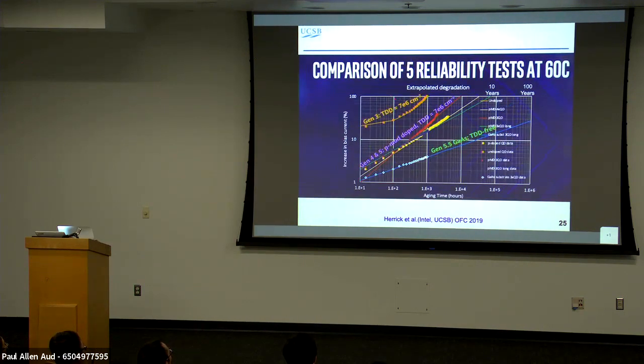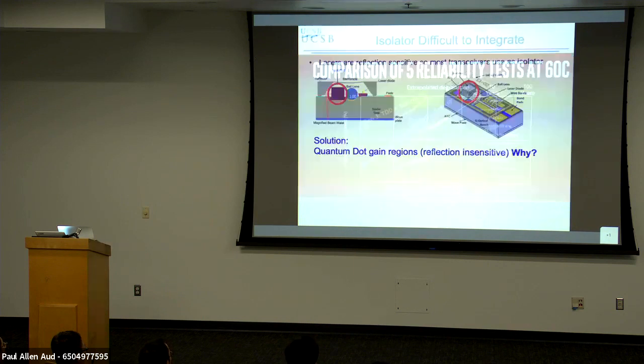And here's the answer. So that previous 7×10 to the 6th that was out to here at room temperature now dies in a few thousand hours. But as you do other things, we're calling Gen 4, Gen 5, they're all p-doped devices. They're on the order of 2 orders of magnitude better lifetime. And so this is kind of where we stand today, around 10-year lifetime in devices at high temperatures. So it's not good enough yet, but it's getting closer. Our quantum dot lasers on gallium arsenide have much better lifetimes. And again, there's no dislocations. So we're still dislocation limited in terms of reliability. So it's improving, but it's not adequate yet for real commercial devices.